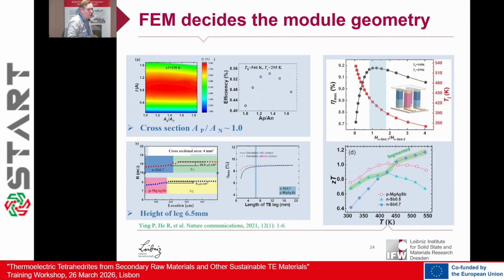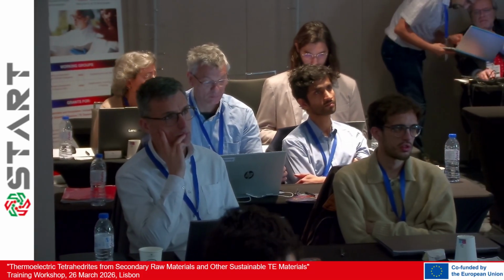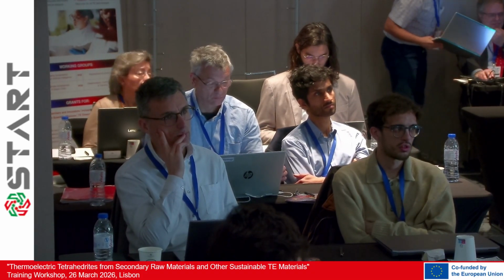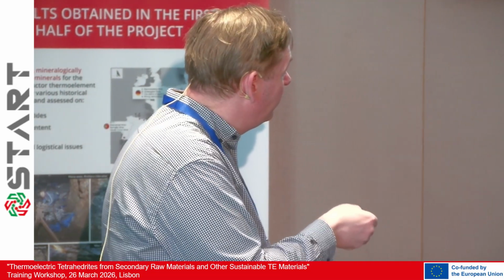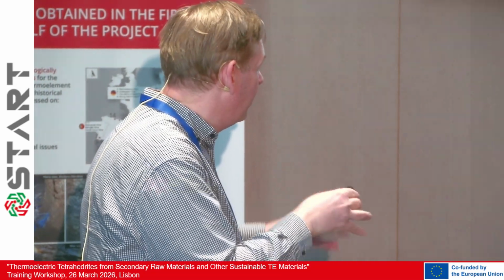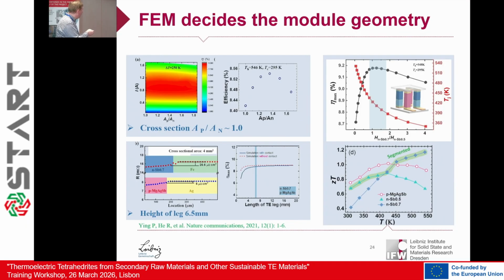What is very important always when we design such a module is that we do finite element simulation. So we simulate the whole device, and we also get a very good fit between our actual fabricated device and the simulations. And you can also play around with the geometrical parameters. In this case, it was not so much necessary to play around with, for example, the cross-section, but there was the idea to maybe optimize it. Here we have to optimize, for example, the height and the segmentation, and you can see you can optimize the performance by the segmentation.